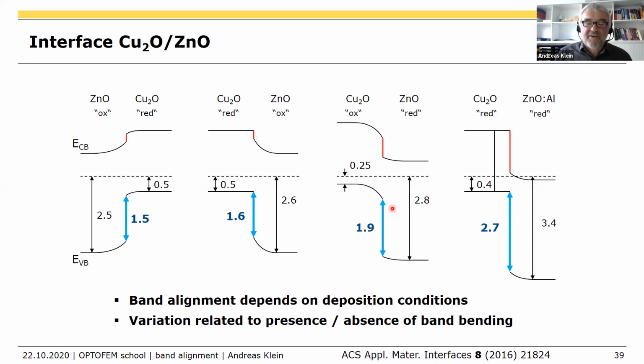And the same with the zinc oxide, we also have oxygen vacancies, which can pin the Fermi energy because there are deep traps there. So they can lead to this modification of band alignment. And also for zinc oxide, we have also seen this directly for Schottky barriers.